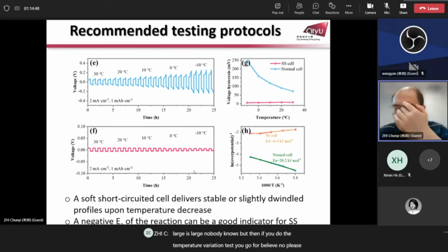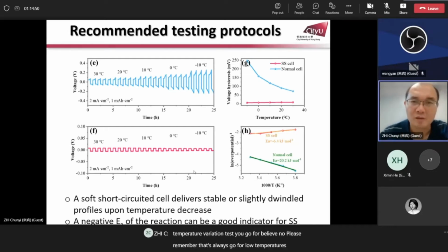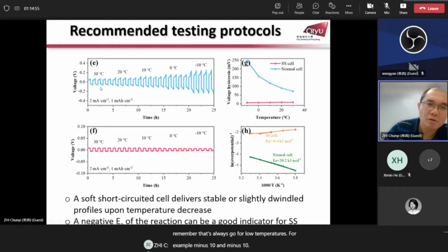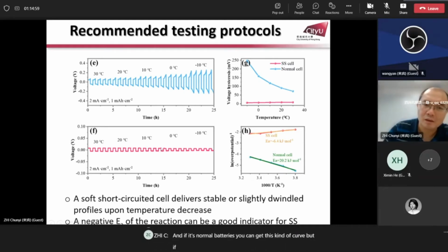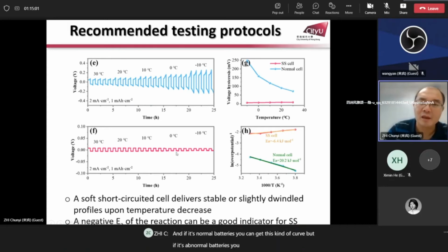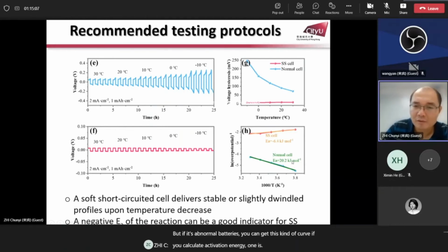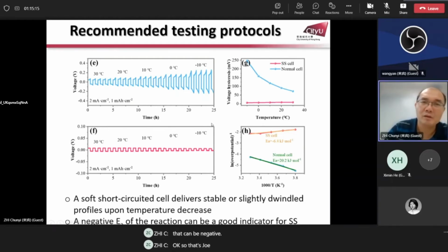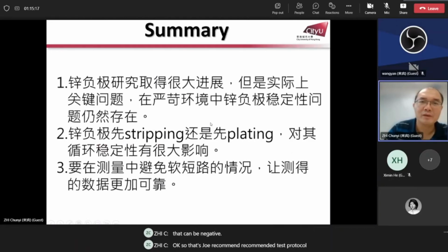But if you do the temperature variation test, please remember to always go for low temperatures, for example, -10. If it's a normal battery, you can get this kind of curve. But if it's an abnormal battery, you can get this kind of curve. If you calculate activation energy, a normal cell is positive, but for soft short cells, it can be negative. Okay, so that's just the recommended test protocols you can use to evaluate.